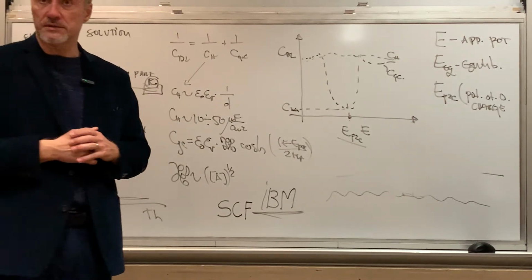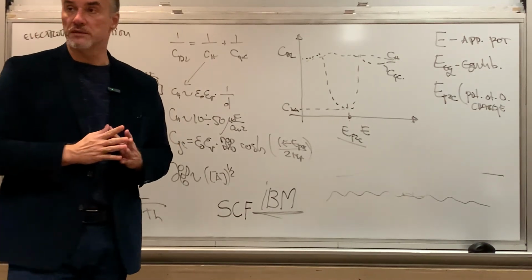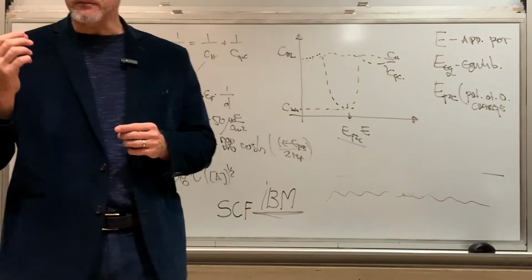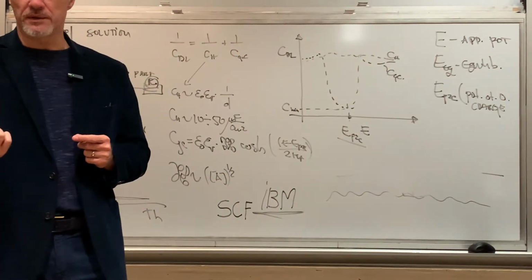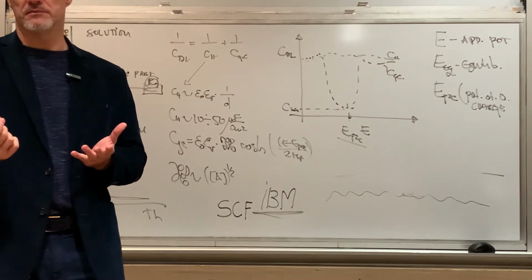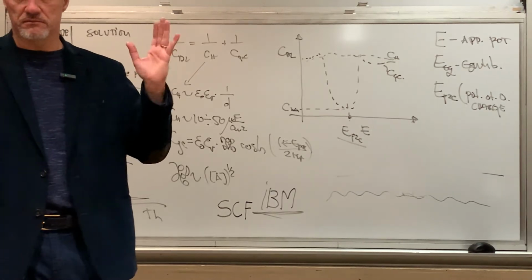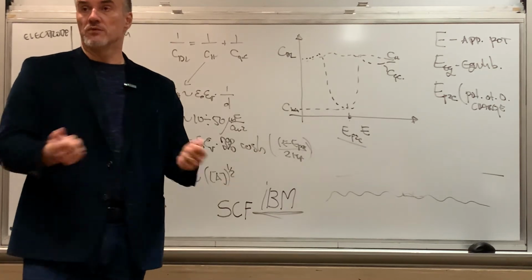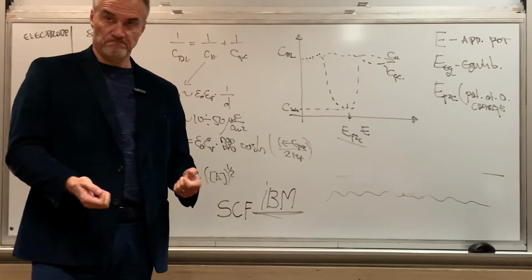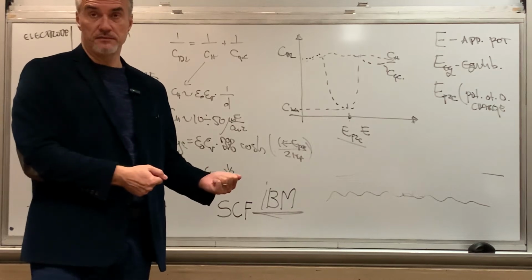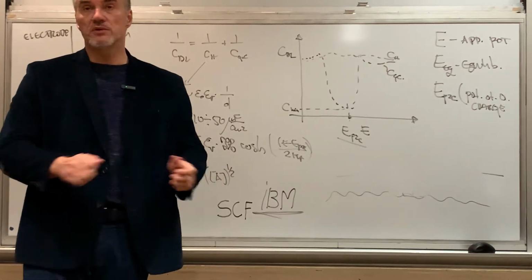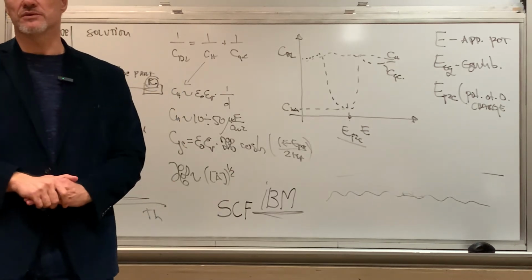If you need hard coatings, I don't know if you heard in mechanical metallurgy there's a Hall-Petch relation. Deposits which have smaller grains are supposed to be harder. That's because of certain things that I'm not going to go into. So here, at will you can grow copper, for example, which is harder, or softer gold, just by simple manipulation of the overpotential.